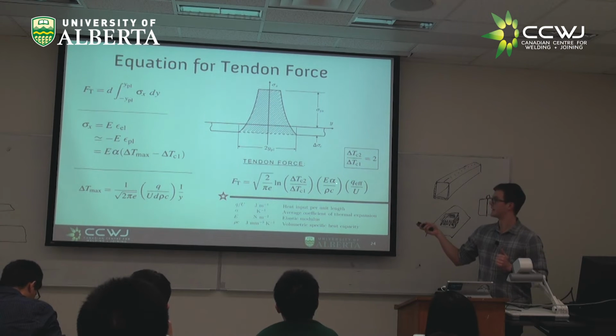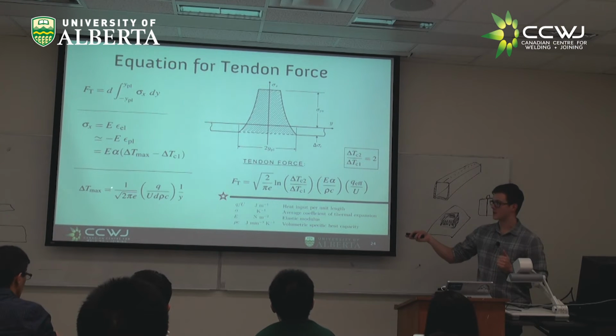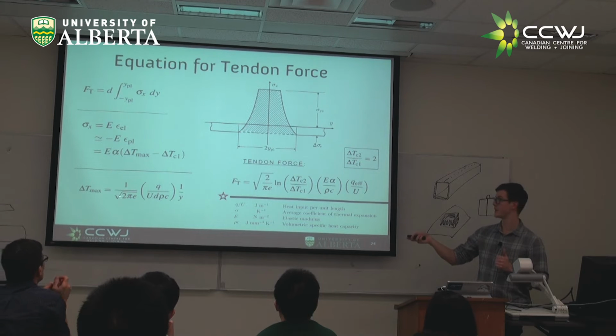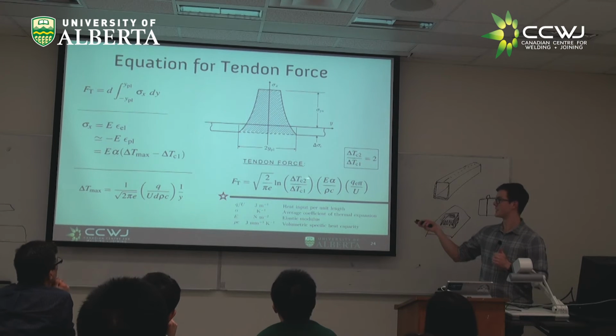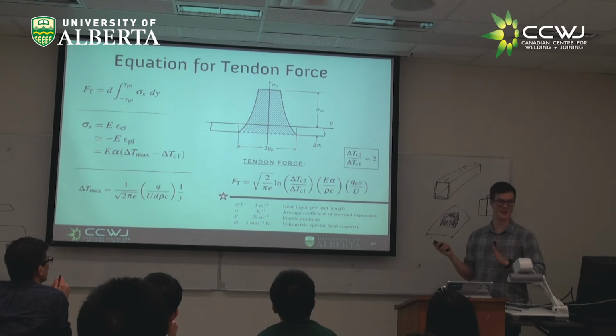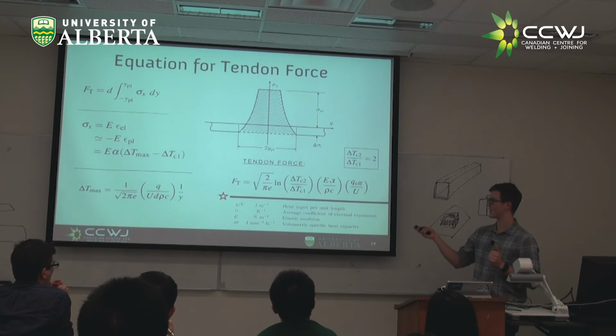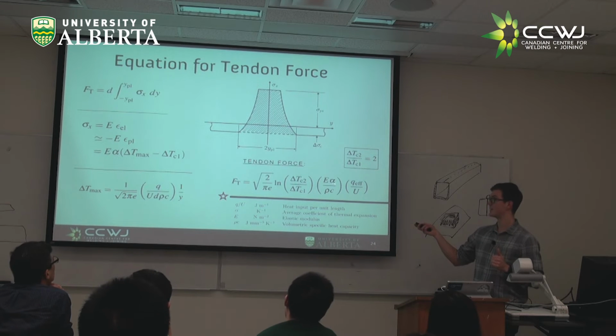Now, the other thing we see here is all of those constants that were in our Tmax expression end up coming into play in our expression here. So we end up with some numbers in front that go with our ln. That's just a constant. That's going to be a number. That's not going to depend on anything. We don't have to worry about that. But what about what we see here? So this is our elastic modulus. That comes from the fact that to get stress from strain, we multiply by elastic modulus. This is our coefficient of thermal expansion. Once again, that comes, yep.